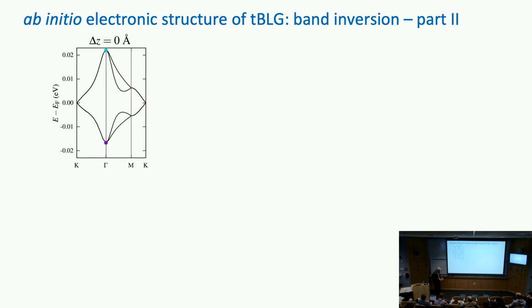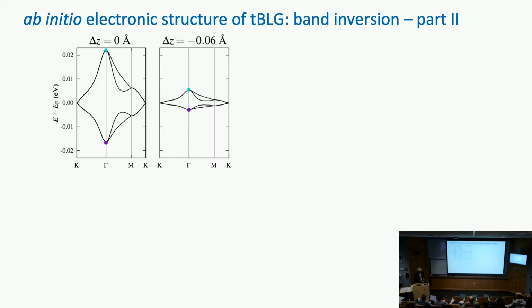I will show you states for what happens when you compress the two layers together. They're twisted, but you do an additional compression of the two layers. It is known experimentally, and actually we had shown from the theoretical point of view, that compressing the two layers is equivalent to shifting the magic angle, the angle where the bands become very flat, to smaller values of the twist. In fact, that was a prediction that we had made that was later verified experimentally by the group of Corey Dean at Columbia. So here's what happens when you compress the two layers. Delta Z equals 0 means no compression at the original separation Z between the layers.